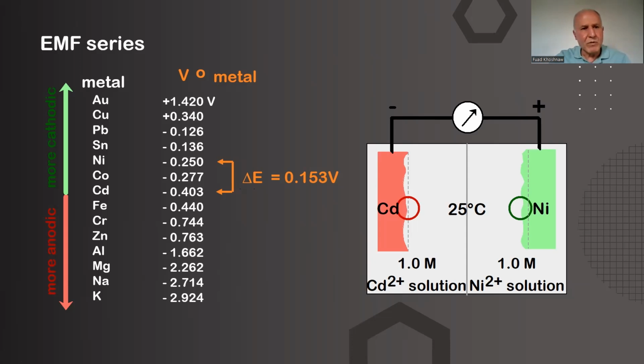So that's a very simple way to avoid galvanic corrosion: to avoid metals that are far from each other. For example, if you have copper and we put magnesium, then the magnesium will very soon be eroding, and that will be used as sacrificial corrosion, because this one corrodes very fast to protect copper, or let's say tin, for example.